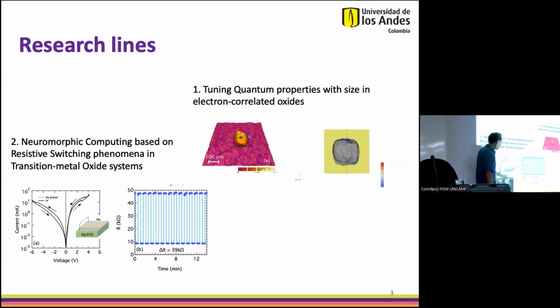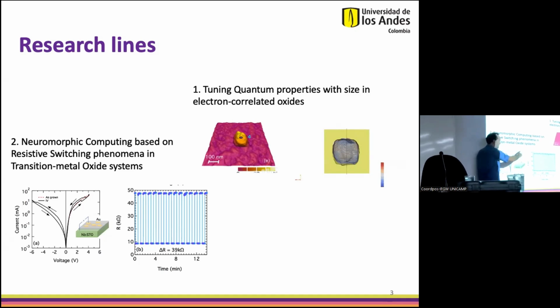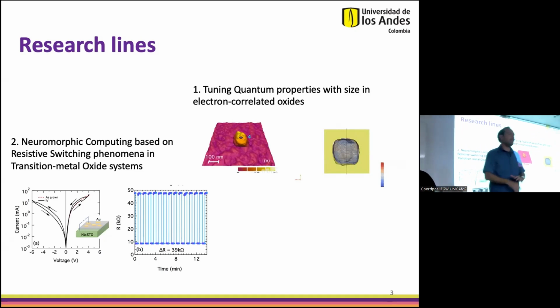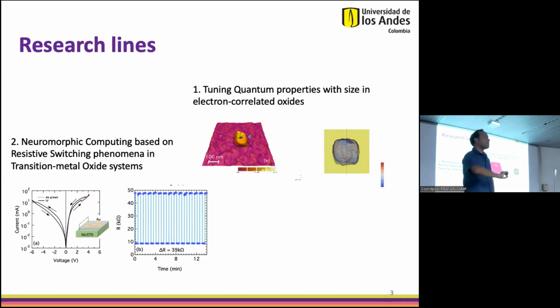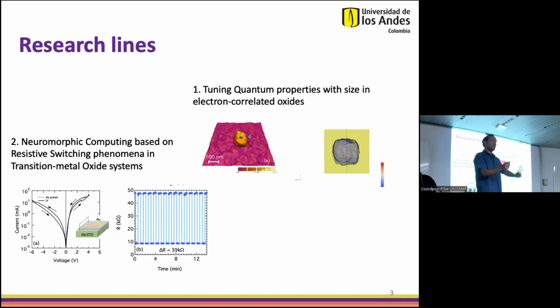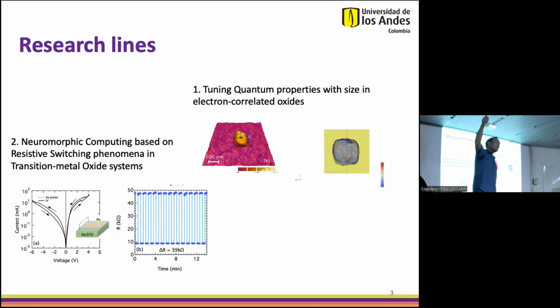What we found is that depending on the voltage you apply, once you reach a certain value in current, the sample changes in a way that is permanent. Think about a resistor: you put a voltage, every time you increase the voltage you get a current, and it's a straight line. Here it's not the same. It's a straight line, and then it changes to a different value of resistance, and it never comes back to the original resistance value. The only way to get that value back is to apply a voltage of opposite polarity on the other side. So this voltage here is a reset voltage.